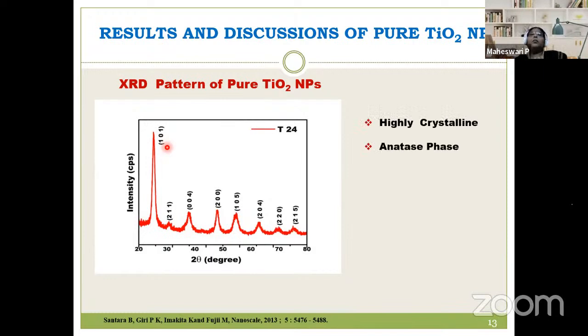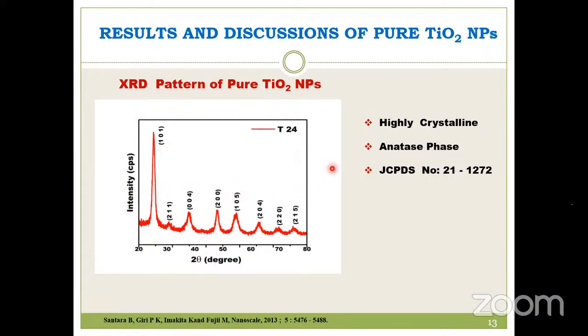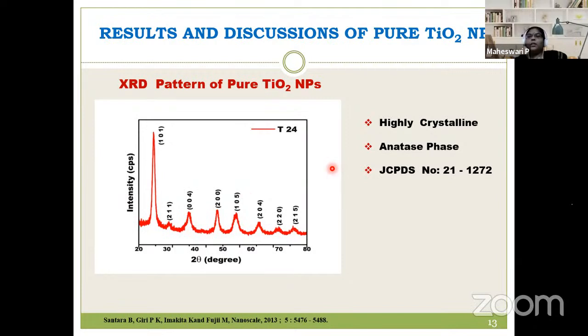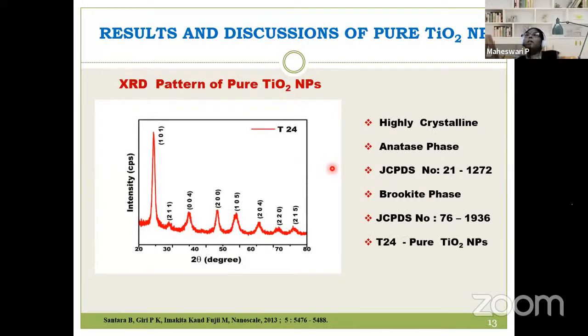And there is a thing called JCPDS, the Joint Committee on Powder Diffraction Standards. All the standardized data is put in this bank. From that, JCPDS file number 21-1272 exactly matches this pattern. Also, we have a mixed phase here: a small fraction of brookite is also available, which again matches JCPDS file number 76-1936. So from the XRD pattern, we have a clear indication that they are highly crystalline in nature.